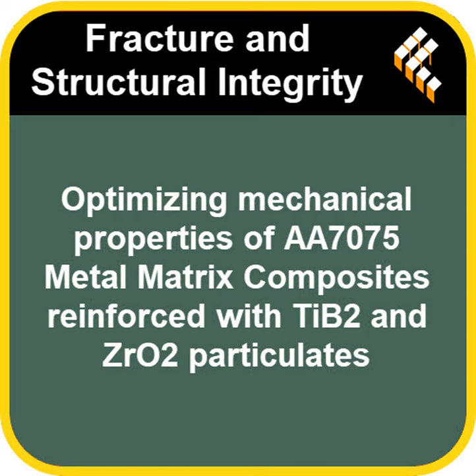So let's talk performance then. How much stronger, harder, tougher did these materials actually get? What did the tests show? The results were pretty dramatic, especially for hardness. So the baseline AA7075 alloy, the starting material, has a Vickers hardness of about 55 HV. Oh, 55. All the hybrid composites showed significant improvement, but the star performer, again, the 5% TiB2, 4% ZrO2 composite, it achieved the highest hardness, 102.04 HV.